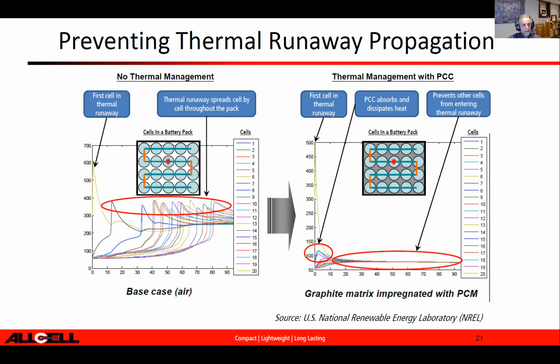Here's one test that we've done. You can see that the pack to the left, which has only air between the cells, once the first cell fails, rapidly goes to thermal runaway and exceeds 600 Celsius in less than a minute. And a few minutes after that, the other cells start popping, or start going through thermal runaway, and that's called the domino effect, until the whole pack catches fire. The one to the right, as you can see, has a phase change composite, and once that cell goes to thermal runaway, the other cells heat, but we managed to keep them below the threshold, and they go back and cool, and the rest of the pack is safe.